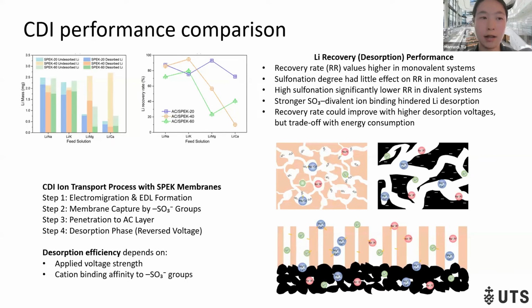And here is the desorption result. Here is a comparison. So the recovery rate values are higher in monovalent cases, and sulfonation degree has little effect on recovery rate in monovalent cases. High sulfonation significantly lowers recovery rates in divalent cases because the stronger binding between the sulfonate group and divalent ions can hinder the lithium desorption. And the recovery rate may improve with a higher desorption voltage, but there is a trade-off with the energy consumption.